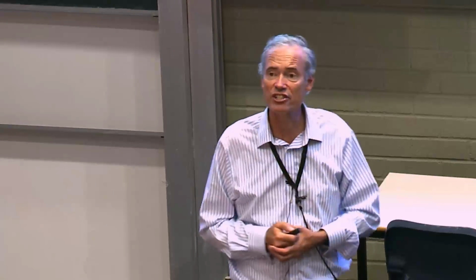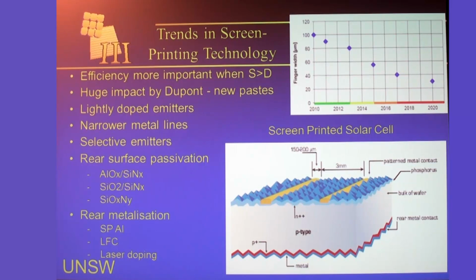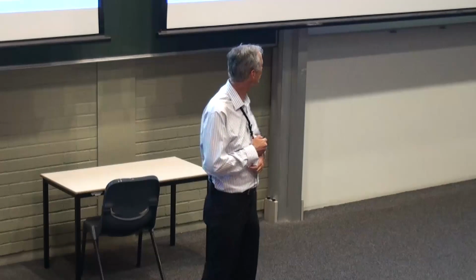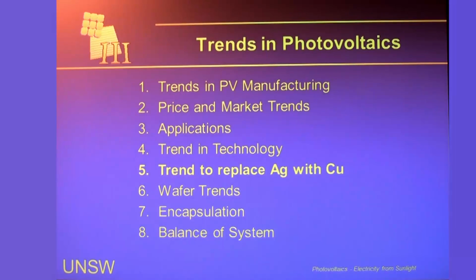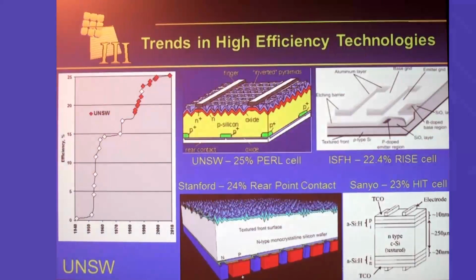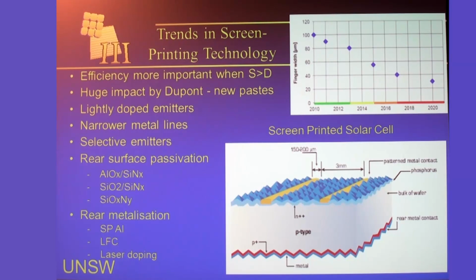We're starting to see some companies going into large-scale manufacturing, like REC, for example, who are now in large-scale manufacturing with aluminium oxide capped with silicon nitride. And in pilot production, we're seeing some quite impressive efficiencies, with several companies now getting to efficiencies in the vicinity of 20%. This is using standard P-type Czochralski wafers. With regard to rear metallisation, most companies have their preferred approach being based on the use of screen printing of aluminium.